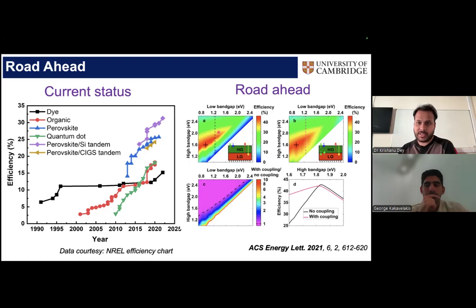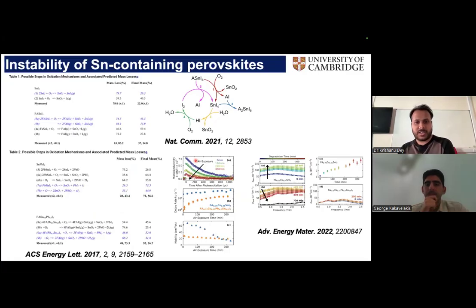which is why we need to alloy lead with tin and make this mixed metal composition to reach that band gap, which is then useful for all-perovskite tandem applications. Now, these perovskites containing tin have some problems, and it's been known for several years now, and it comes from the basic chemistry. As you would already know, because of the lone pair effect, tin wants to be in the +4 oxidation state, whereas in the perovskite structure, it is forced to be in the +2 oxidation state.